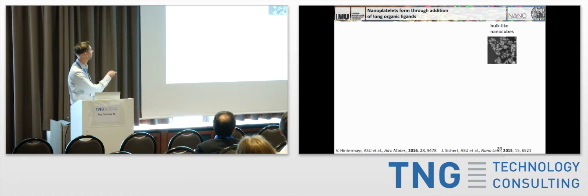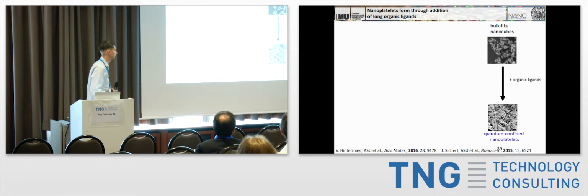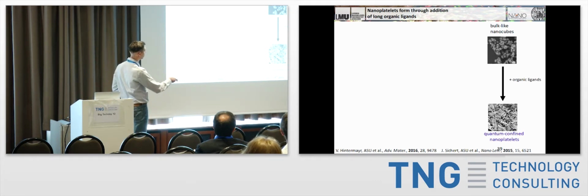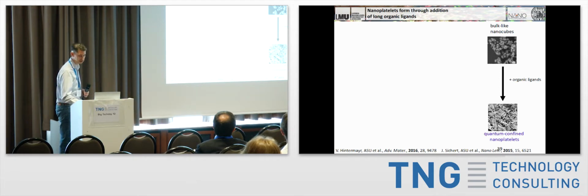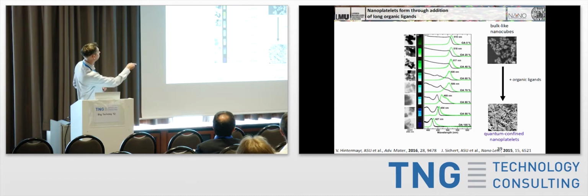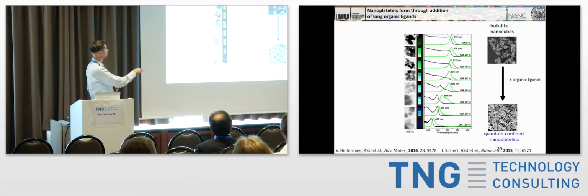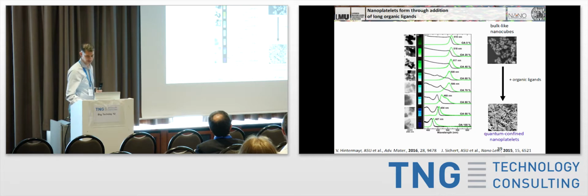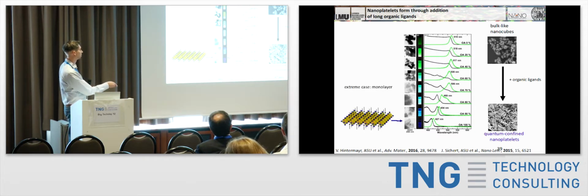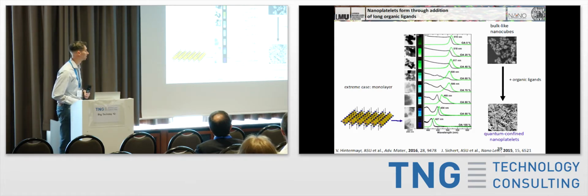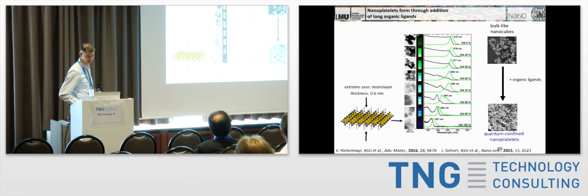And they were using long organic ligands to passivate the nanocrystals. And so what we found is that as we added these organic ligands, instead of the crystals getting smaller and smaller, what we were doing is we're transferring these cubes into quantum-confined nanoplatelets, very, very thin nanoplatelets. And to look at how this affected it, essentially we're starting out from these bulk cubes and then adding a percentage of the organic ligands in there. And as you can see, as the content goes larger and larger, you can see the color of these actually shifts. And from TEM images here, you can see it's thinner and thinner. And so essentially we're going down to very, very thin nanoplatelets. And in this case, actually, of the 100% organic ligand, what we're seeing there is actually a single monolayer, which in this case is only about 0.6 nanometers thick. So extremely thin layers.